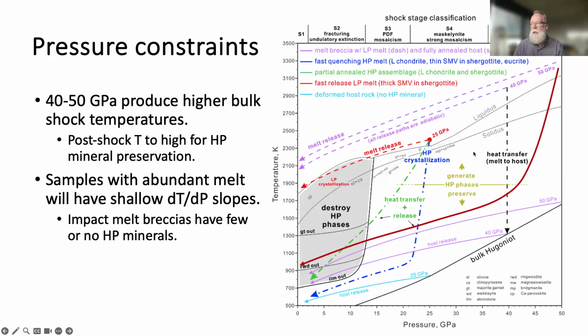And so what we see is that we don't have samples. The samples that have been shocked to very high pressures are probably impact melt breccias that are dominated by low pressure minerals and quench of shock melt after pressure release. But this really shows that we can't really get the high pressure minerals we see from a decompression path.